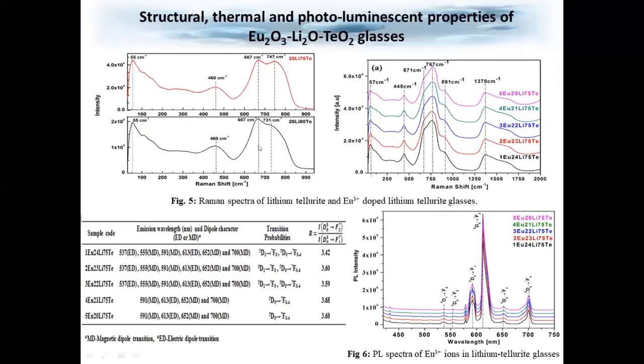And these are the Raman patterns in the low wave number region from 30 to 900 centimeter inverse. And these are also the Raman patterns in the higher wave number regions for europium doped samples. For lithium tellurite samples, we don't see any peak around 1370 centimeter inverse. Actually, these are not Raman bands, but these are photoluminescence peaks, which arise when you excite your europium doped lithium tellurite sample.